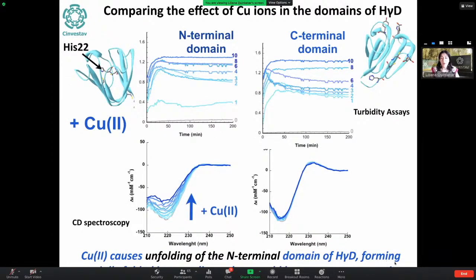We can also construct the separate domains, the N-terminal domain and the C-terminal domain, and in both cases, turbidity assays indicate that copper can induce the aggregation. But in the circular dichroism experiment where we see folding, only the N-terminal domain is susceptible to unfolding caused by the metal ion. The C-terminal domain remains intact.